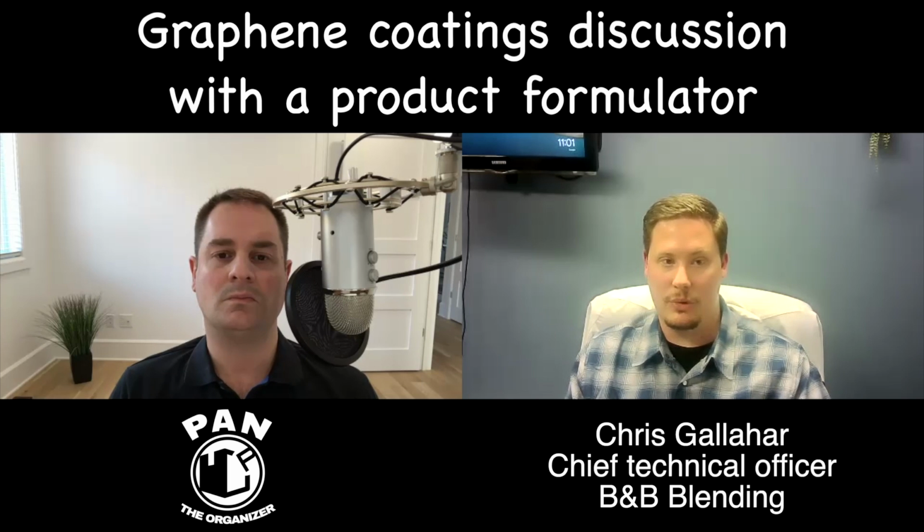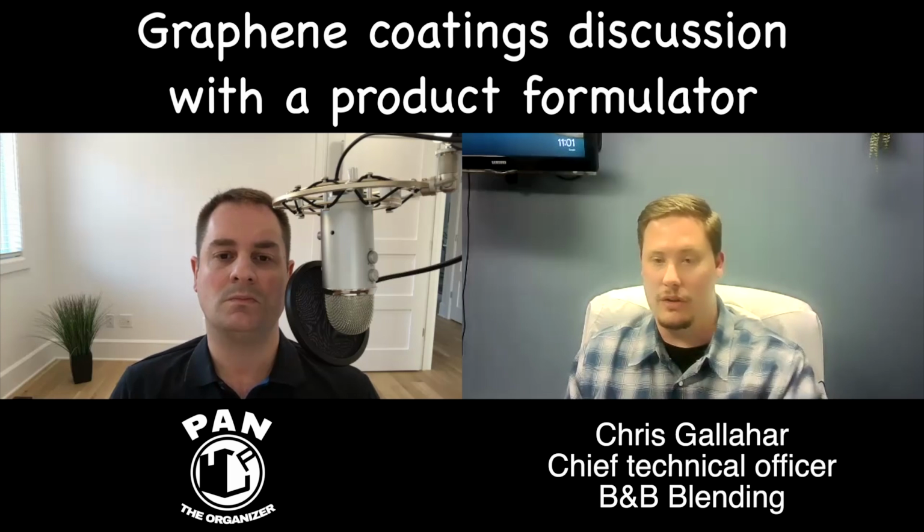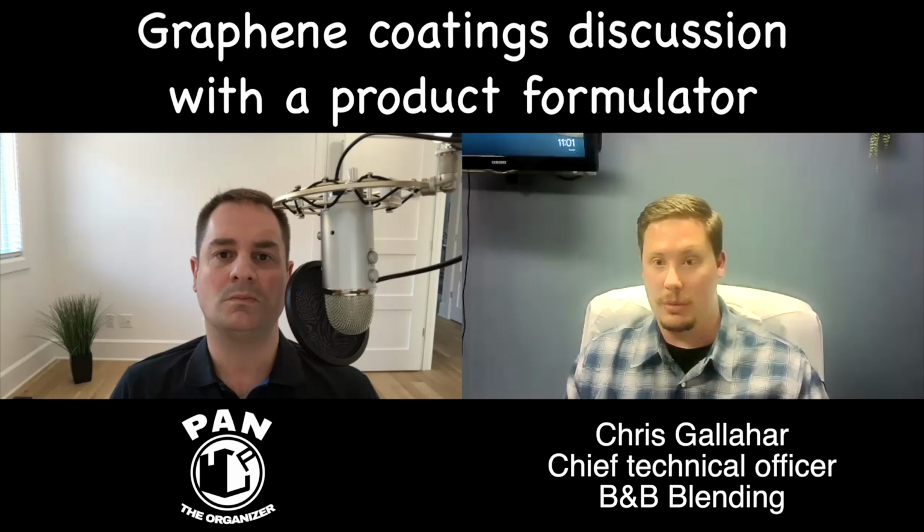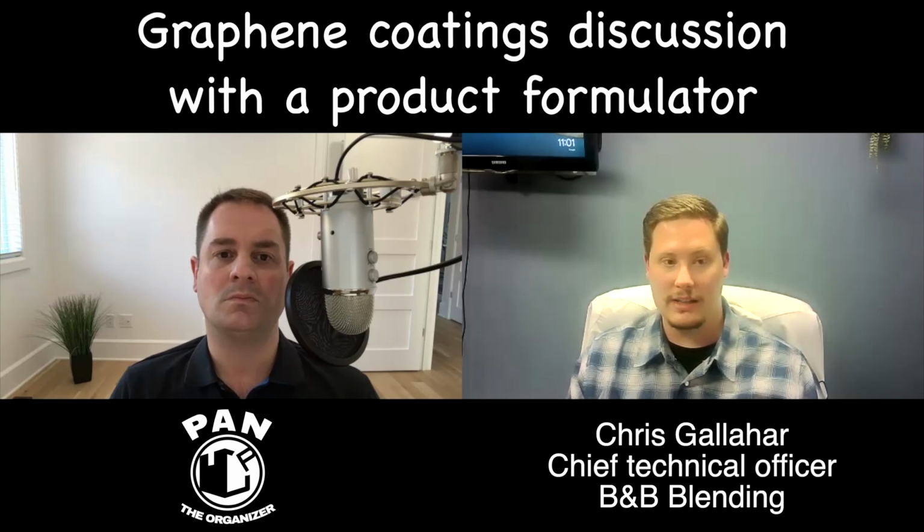So from a formulary standpoint, we're building our formulations with a baseline in mind. So we might have an instance testing resins one-to-one. We have a quartz coating where we've got it loaded in the formulation at a specific loading level. And then we have a new incumbent resin that's coming in saying, I have graphene oxide, so does it actually perform better? And we're putting it through a battery of tests. Is it slicker, AKA, does it have a lower coefficient of friction? Is it actually more hydrophobic, i.e., does it have a higher contact angle?